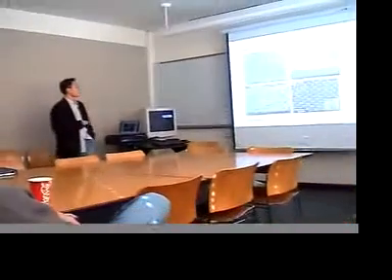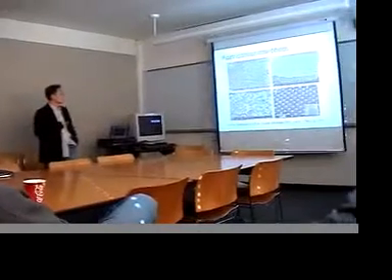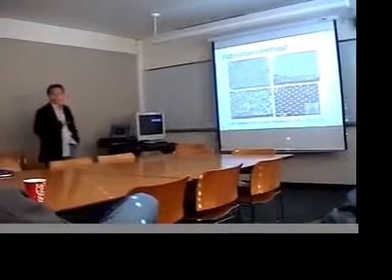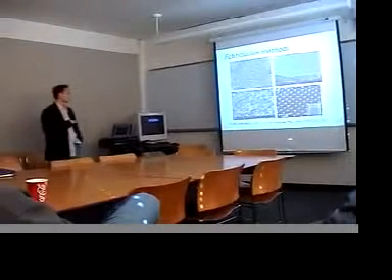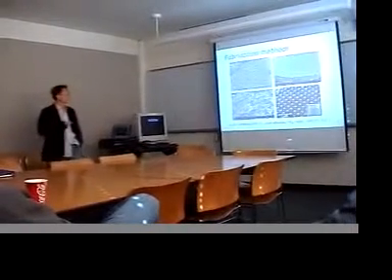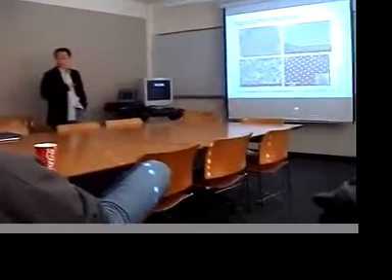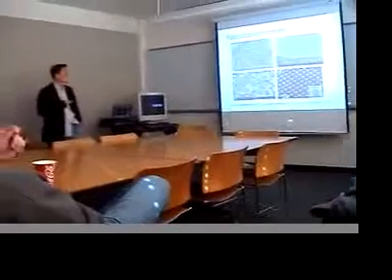So these are SEM images of the various methods that are used. As you can see here, with arc synthesis and laser ablation, your end products are all bundled up and entangled. So this is quite a problem because you need a pretty elaborate post-treatment process. And also with arc synthesis, the yield is not very good. You have a lot of other forms of carbon, such as fullerenes.